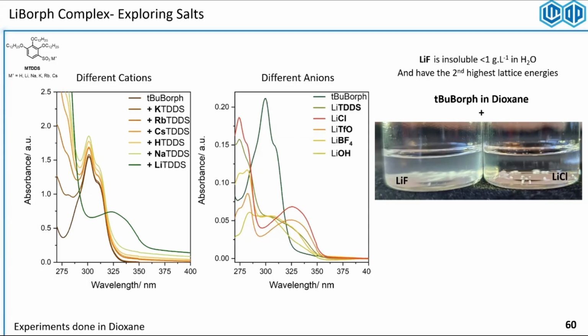Even though they're very insoluble in organic solvents, the macrocycle can selectively go and bind to these and extract it from the salt crystal. We also did a test with many different soluble salts, where we can now control the concentration. It's not just a bunch of crystals added into a vial.